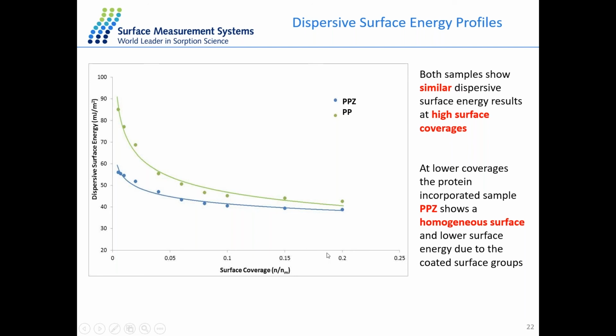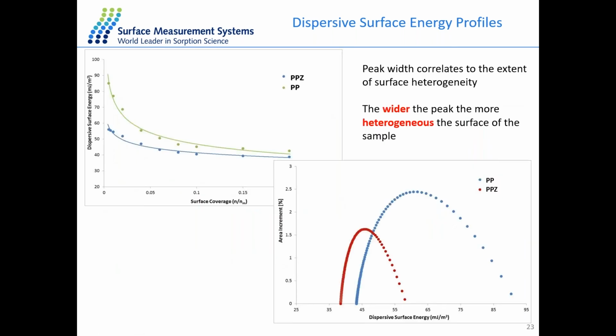And what we can see here is that our polypropylene with the zein protein has a lower dispersive surface energy compared to polypropylene on its own. So what this is telling us is that with the introduction of the zein protein, we're lowering the surface energy of the material. What we can also see, by looking at the infinite dilution region, is that the polypropylene on its own has higher surface energy sites, which we're able to access using our probe molecules. So in this regard, we can already assume that this material is much more heterogeneous. If we plot the distribution, we see that that is apparently so. So the wider the peak, the more heterogeneous, and the narrower the peak, the more homogeneous.